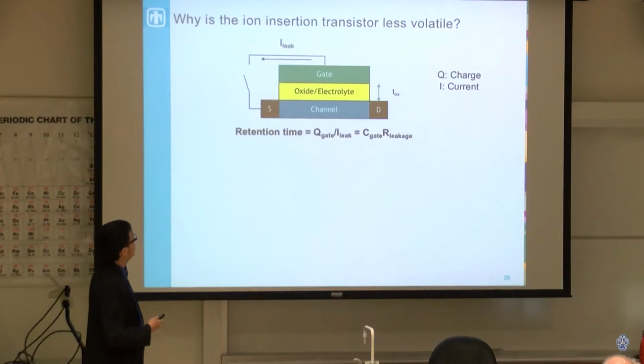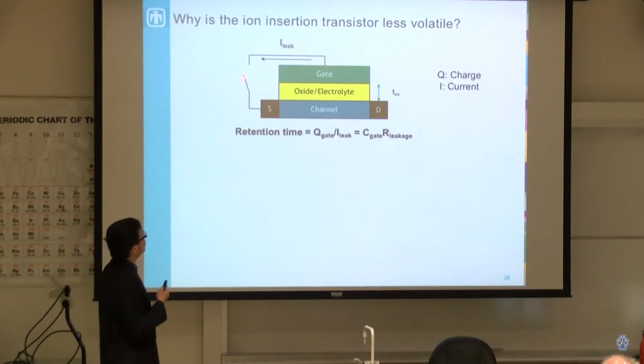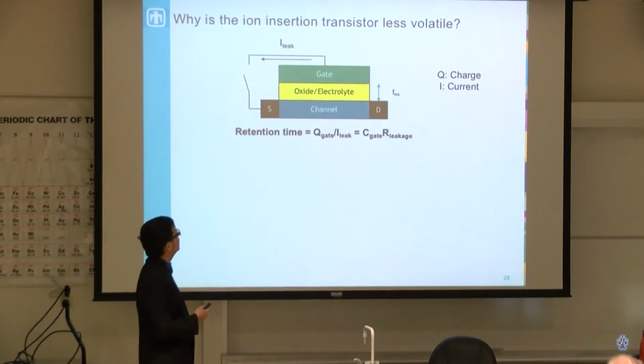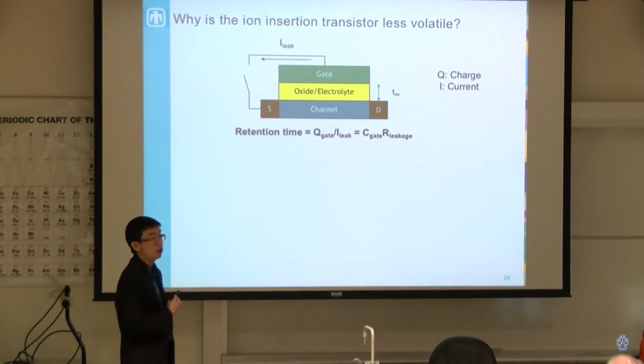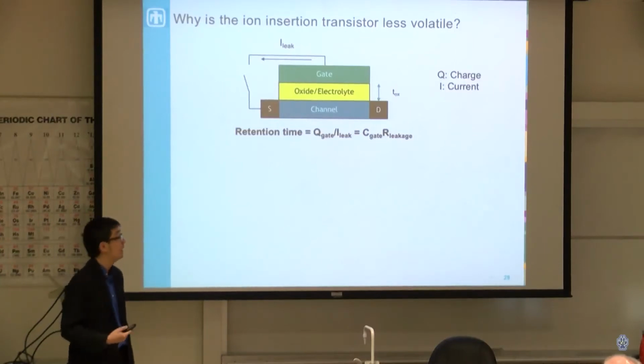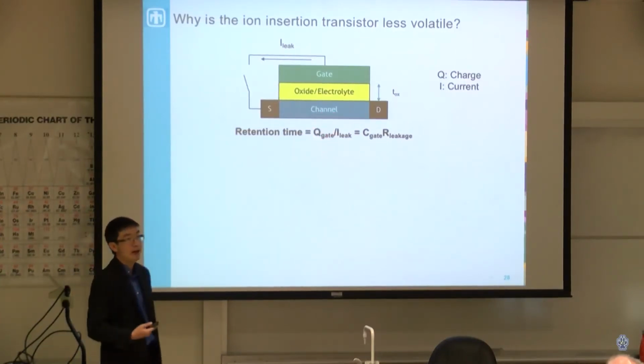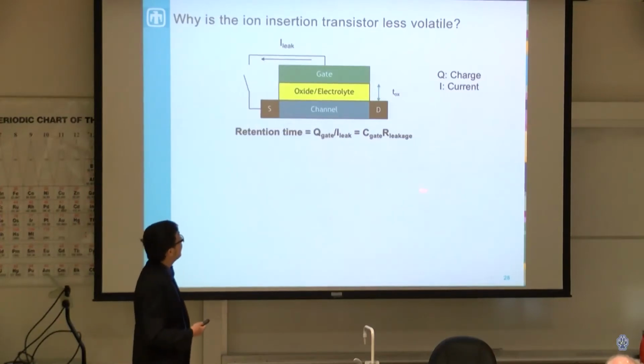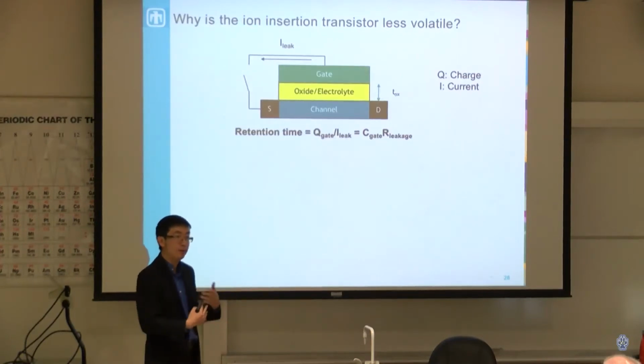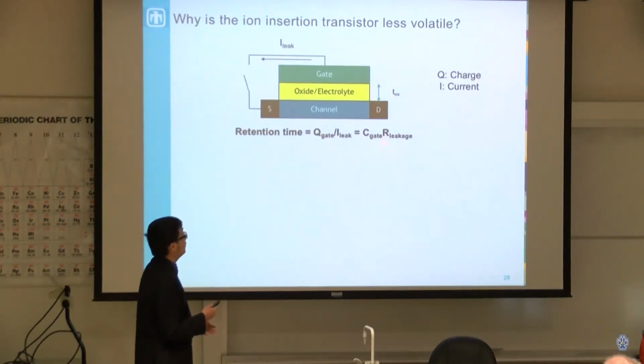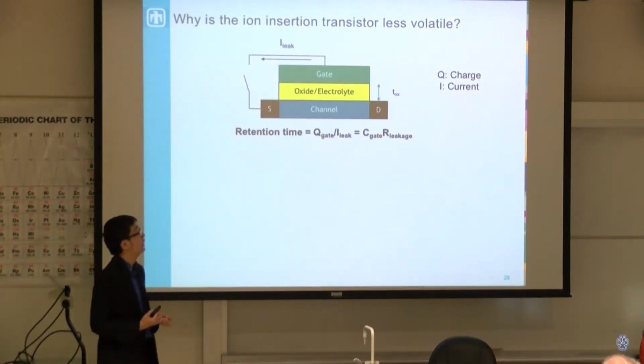So our retention time is basically the amount of charge you have on your gate electrode divided by the leakage current. We can put a switch here, but no electronic switch is perfect. As a result, we have this leakage current that goes through the outside. So the retention time is how much charge you put divided by the amount of leakage. Another way you can think about it is the capacitance of the gate electrode, so how much charge you can put on it per given unit of voltage, multiplied by the resistance, whatever resistor you put in here that dictates your leakage current. So it's just the RC time constant here.